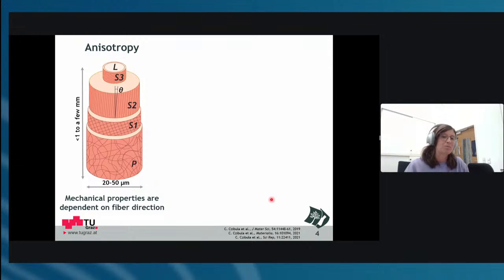First, on the anisotropy. So we know that all these fibers, and this is just a general scheme, I mean, it's not a very beautiful one, but we can take this general: the fiber has a hierarchical structure and it has anisotropic properties. And when we now do tensile testing, for example, we will always be only able to get information on the axial direction of the fiber.